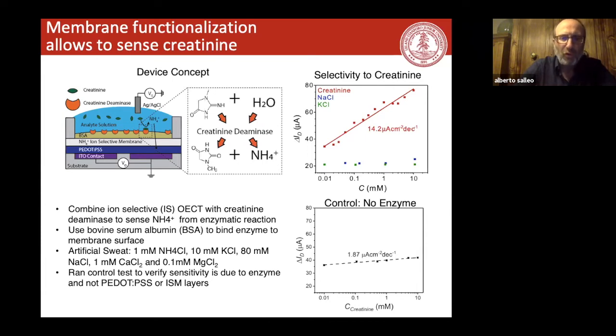Again, full disclosure, the creatinine deaminase after a while desorbs from the BSA, so this is not the best way to do it, and it also degrades after a while. There are better ways of doing it, but this was a nice demonstrator that you can use an enzyme as well with this type of device, which is not obvious because you have here a big barrier layer, so you might wonder whether this will interfere with the operational device. It turns out it slows it down a little bit because there's a little bit of a barrier now for the gate signal to go down, but it doesn't significantly degrade how the device works.